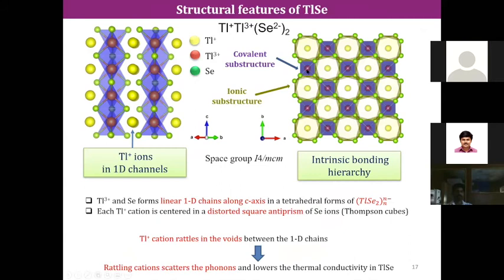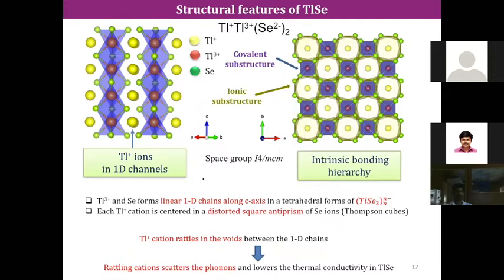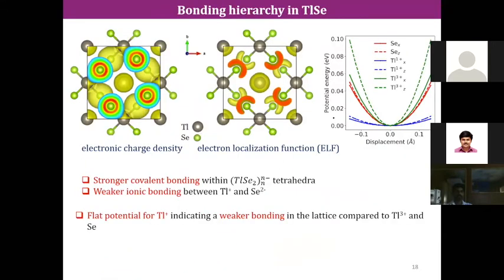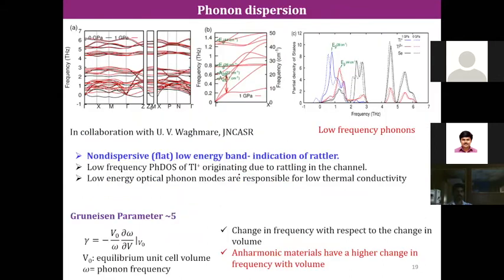17th slide, right? So this part was clear, right? Like how we talked about the rattler from this weak ionic bonding, and from there, as I told you, it's in a very shallow potential well, this thallium atom that actually gives rise to rattling. And as you can see from the phonon calculation, these three modes start from 0. This is the real phonon calculation for this compound. These are acoustic modes, and you have these optical modes which are coming from this rattling.